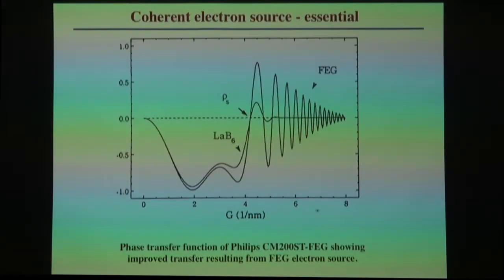So what is essential before you can do aberration correction? You can't just say, okay, I'm going to correct the aberrations. You need to have a coherent electron source. It's essential. Because if you have the regular lanthanum hexaboride, the crossover, the transfer function here, there's not much information beyond the first zero of the transfer function. There's not much point in trying to improve the resolution because there's not much information out there. But if you have a field emission gun, there are albeit oscillations in the transfer function, but the envelope functions tell you that there is certainly considerable information out there at higher spatial frequencies. Higher spatial frequencies means better resolution.